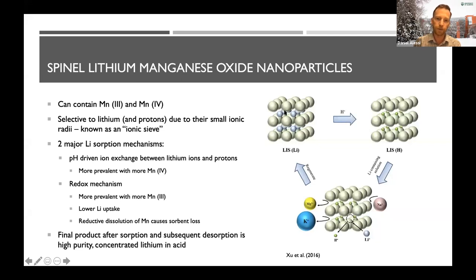So I load it up with lithium. Keep in mind, I've got a big volume of brine and a relatively small amount of these manganese oxide nanoparticles or bound particles in the solution. Once that process happens, it might take half an hour or so, I void the rest of the brine, and the lithium-depleted brine is sent away for disposal. And I've got this powder that's taking up, well, now it's wet, but it's taking up a lot less space. I would add a little bit of acid, a relatively weak acid it ends up, and that's called the protonation step. And so what happens then is the protons, the H plus, kick the lithium back out into solution.